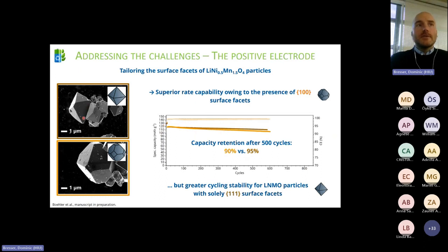And when we do a comparison of these two materials, processed into electrodes and then cycled here for more than 500 cycles, you can see that if we have these 100 truncated surfaces, then we have a better rate capability, in fact, because lithium-ion diffusion and charge transfer across these surfaces is supposed to be favored. But with these purely 111 surface faces, we can improve cycling stability, right, as you can see here. So capacity retention, where we have 95% versus 90% for this truncated material. So you see, it's quite complex to not just synthesize these materials, but really to design the particles to a level where we can optimize performance quite significantly.